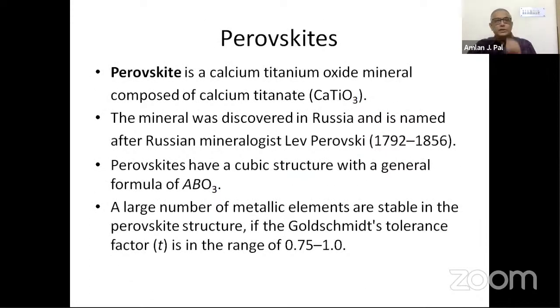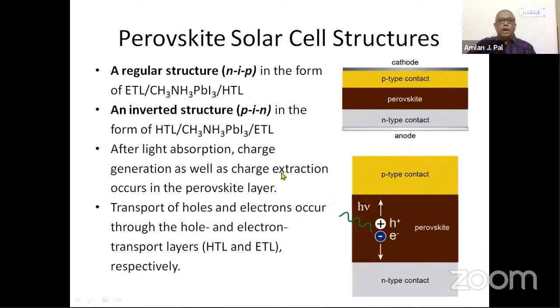So perovskite is a very common name, because the perovskite name has come from a Russian mineralogist, and it has a common ABO3 structure, and a large number of metallic elements are stable in the perovskite structure. There is one formula I will show you later, that the Goldschmidt tolerance factor is in the range of 0.75 to 1. So you can just imagine, you can take the periodic table, for example, and try to form this kind of ABO3 structure, and then you get a perovskite, which is mostly a cubic structure.